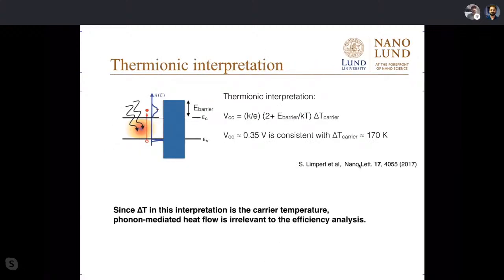One can understand this voltage that we get actually very simply. If we do a very simple estimate, if we simply assume we have hot electrons here and cold electrons here, and there's a thermionic barrier in the middle, then what temperature difference would correspond to that voltage? And that's a temperature difference of 170 Kelvin under illumination. And that is very reasonable. This is what people see in photoluminescence experiments as well. If you blast light onto such a system, the carriers will be hot on average in a steady state. So this is actually within expectation. Interesting is that this effect is enhanced in nanowires because the cooling process is probably hampered by phonon bottleneck type things. But yeah, so this sort of checks out.